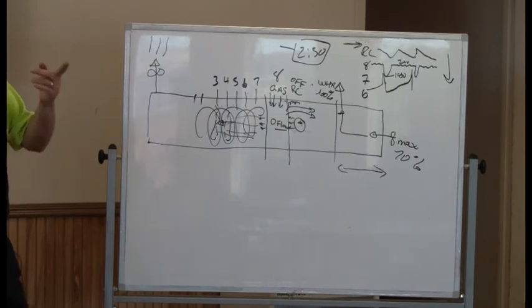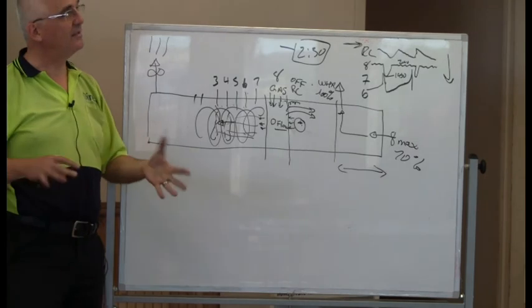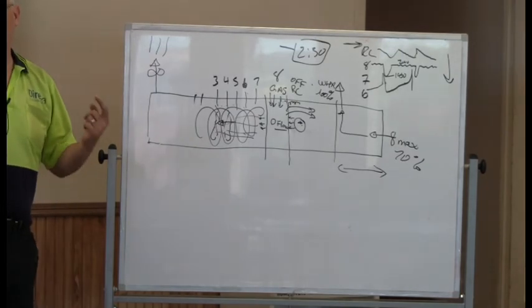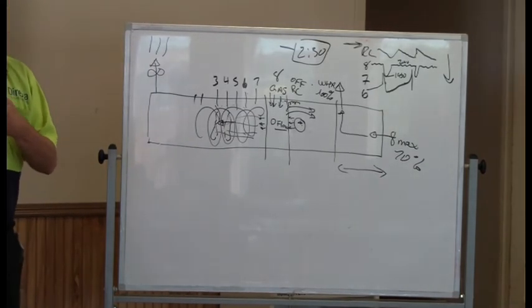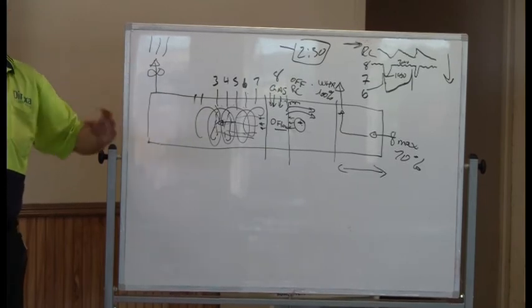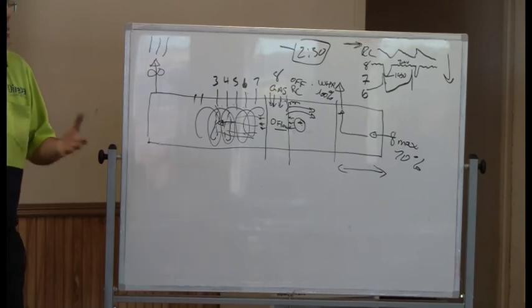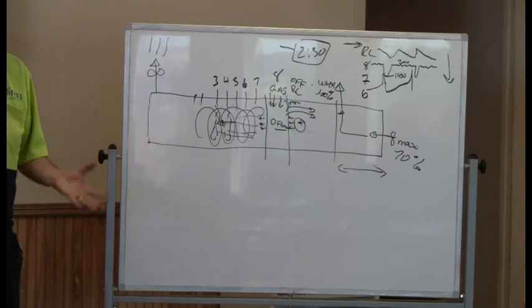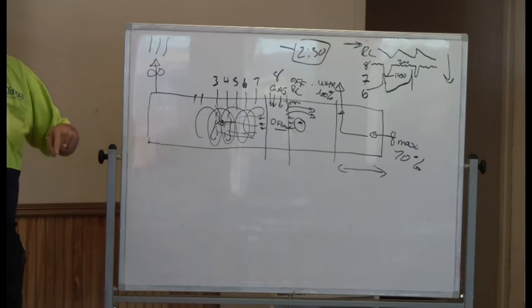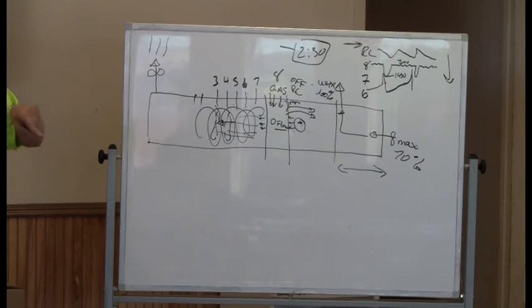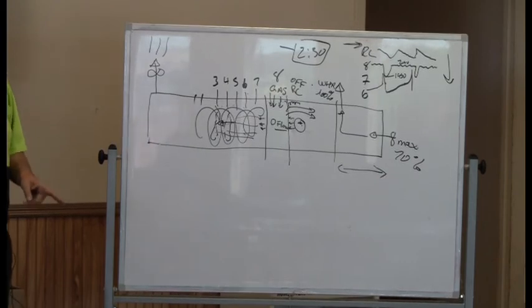That's always difficult, and that's where the undercar has to also be not pushing too much, and that's why I was telling you on the kiln I'm used to, we basically drop down the undercar, we make sure that we are not actually pressurizing as we would normally, because we don't want developing oxygen at the bottom of the car and burning. Actually, that's a great way of burning the skirts, with oxygen. Just bring a bit of oxygen in flashing under your car on the side and ooh.